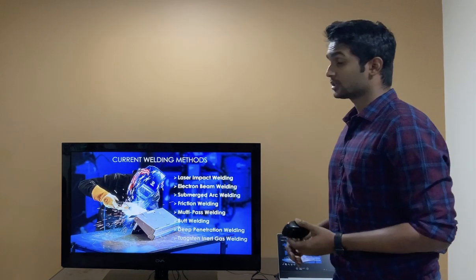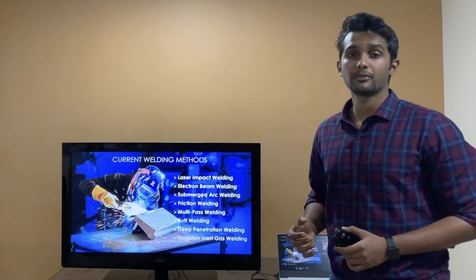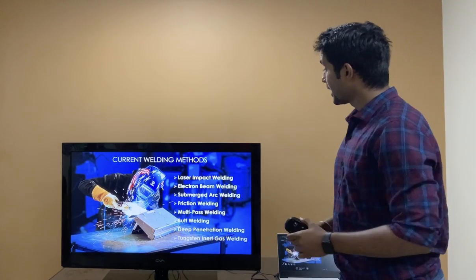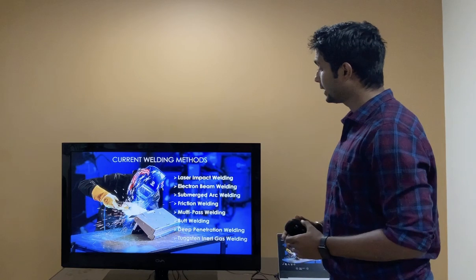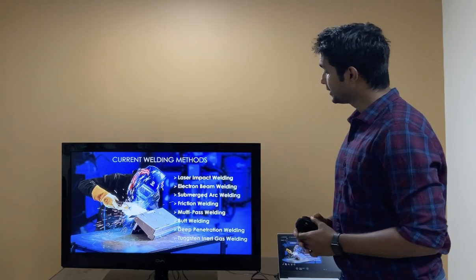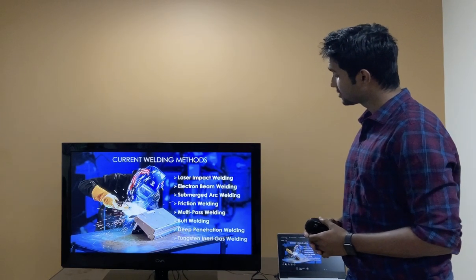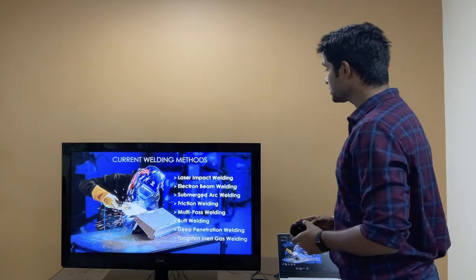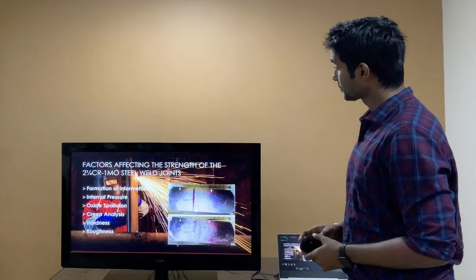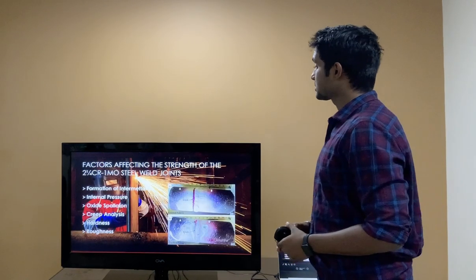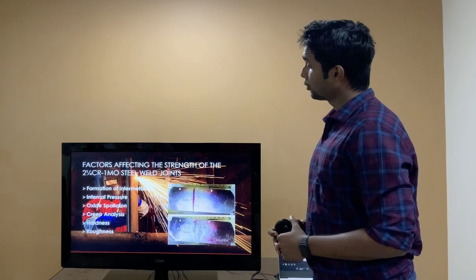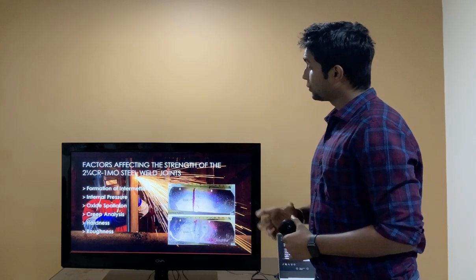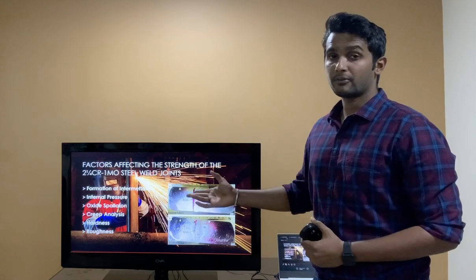The friction welding, which is carried out using the friction part of both metals, and we do have the multi-pass welding, the butt welding, the deep penetration welding, as well as the tungsten inert gas welding. So moving forward, factors affecting the strength of the 2.25 chromium molybdenum steel weld joints. We do have a couple of factors here.